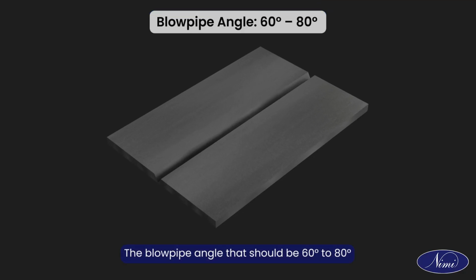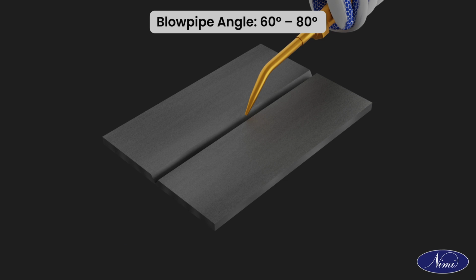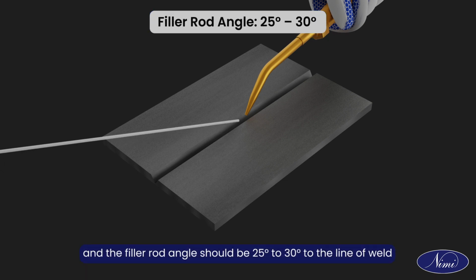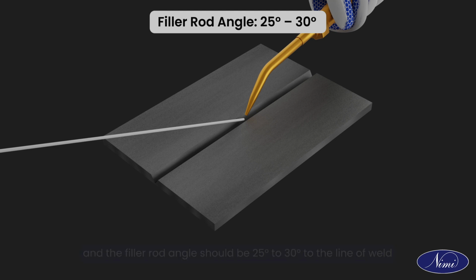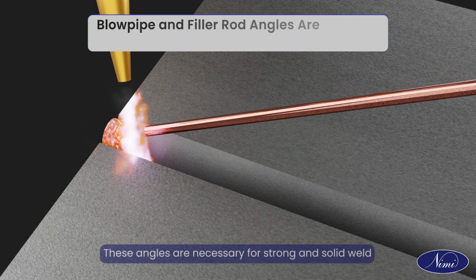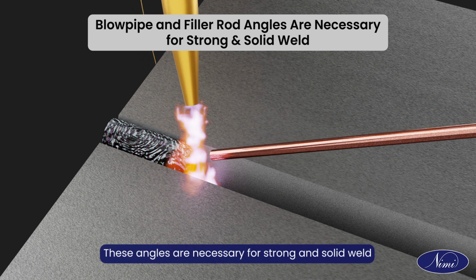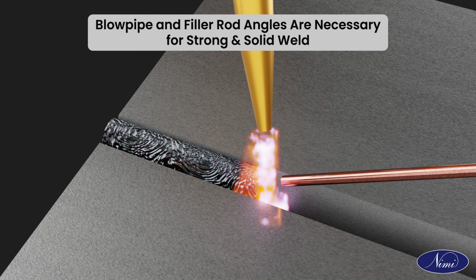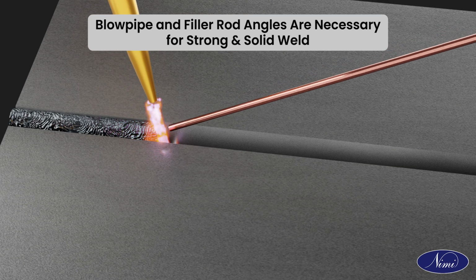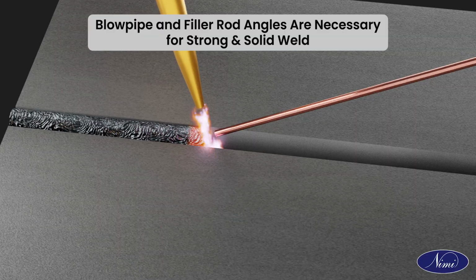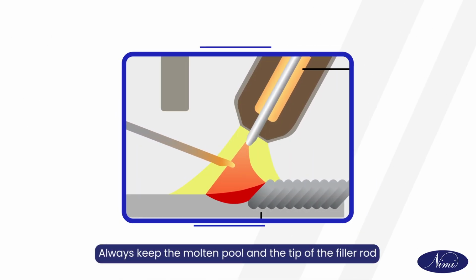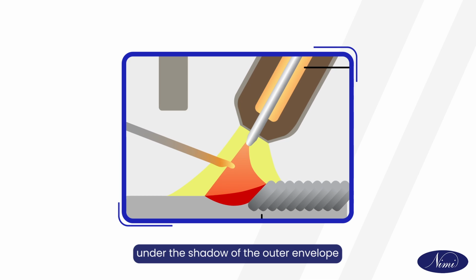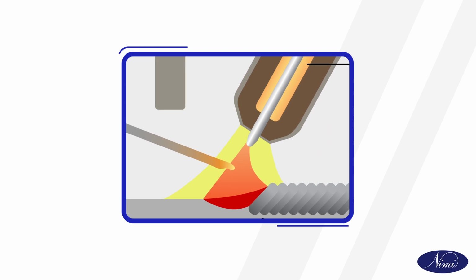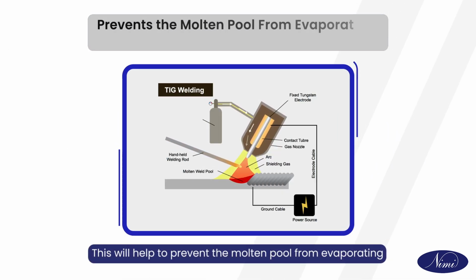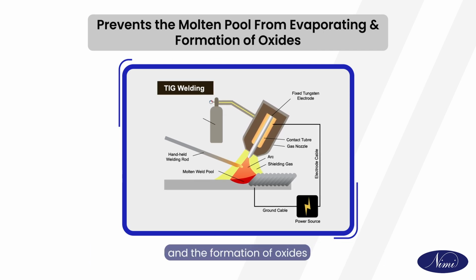The blowpipe angle should be 60 degree to 80 degree, and the filler rod angle should be 25 degree to 30 degree to the line of weld. These angles are necessary for a strong and solid weld. Always keep the molten pool and the tip of the filler rod under the shadow of the outer envelope. This will help to prevent the molten pool from evaporating and the formation of oxides.